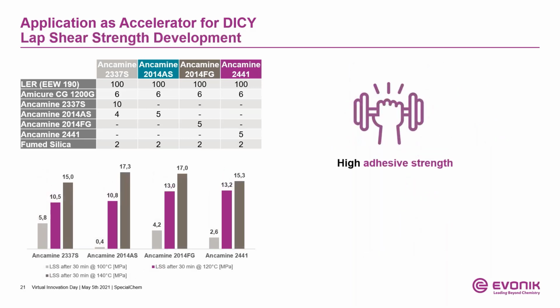Taking now a look on the achieved lap shear strengths after curing at different temperatures for 30 minutes, this time in a temperature range from 100 to 140 centigrade. Ancamine 2337S shows the best performance at curing temperatures of 100 centigrade, which again emphasizes the high potential of it for low temperature applications. Against this, the other modified aliphatic amines perform a bit better at higher curing temperatures.